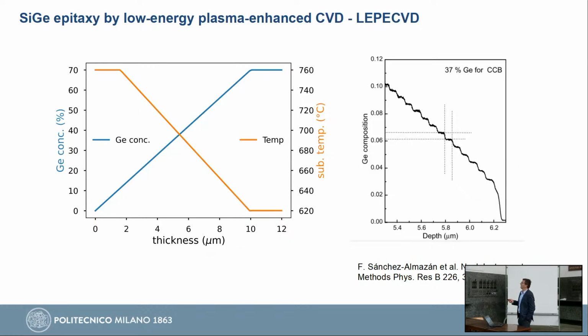So what we typically do in our growth of silicon germanium, we work on these 2 parameters, temperature and deposition rate. And so, for example, if we want to grow a layer like this one, where we essentially increase the germanium content linearly from 0 to 70%, to stick to the case before, at the same time, we reduce the temperature continuously. And we can actually very finely control the composition by this method. Actually, this is data taken here several years ago. Probably Enrico remembers. So this is SIMS analysis of this sample. So we are looking at the tail of this sample. You can see these steps. These are the individual variation of gas flux. So our mass flow controller, the tool that delivers gas to the system, works in steps of 0.1%.